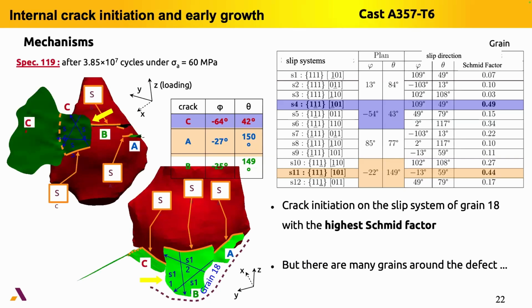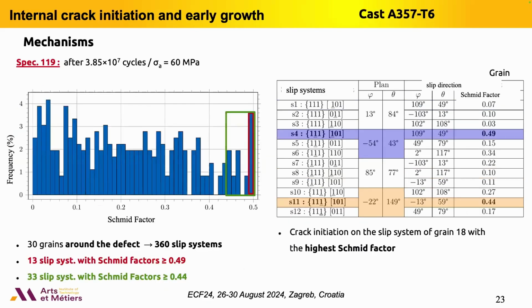But in fact, around the defects, there are many grains. There is not a unique grain. So we have computed in all the grains and all the slip systems around the defects. In our case, there were 360 slip systems, and we observe, in fact, that around the defects, the distribution of the Schmid factor is the following, and there are 13 slip systems with the Schmid factor very close to the possible maximum, very close to 0.5. And there are 33 slip systems with the Schmid factor higher than 0.44. But nevertheless, we will see why the cracks have the observed configuration.